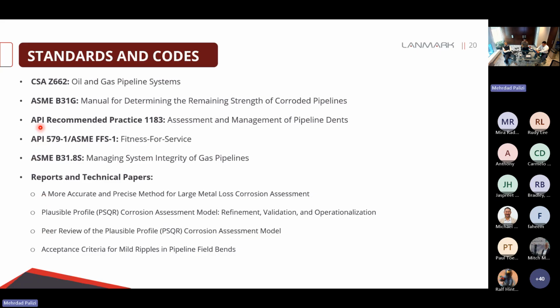Dents are assessed based on API 1183. API 579 is used for assessment over cracks and weld issues that are behaving like cracks. In order to do this, we are using Part 9 in this standard. We are also using Annex 2D here to do Level 3 assessment over corrosion. And finally, we have ASME B31.8 supplementary material that is providing us the basis for doing categorization over defects.